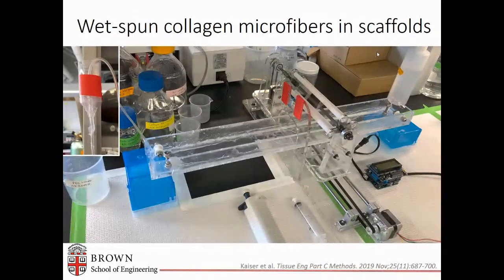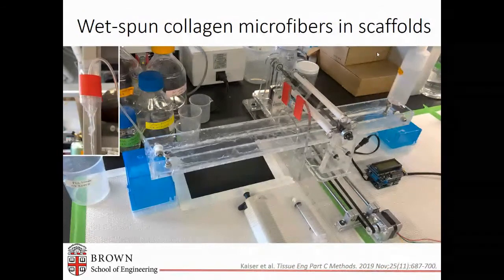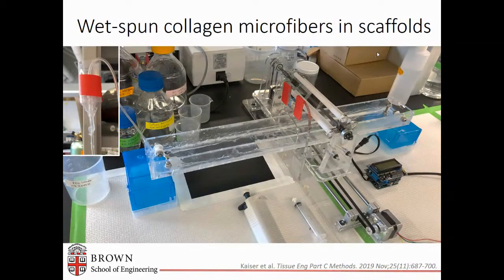In order to provide some geometric cues for elongation and orientation of the cardiomyocytes, we had been using posts, and now we're moving to microfibers. So we're using a technique called wet spinning to create collagen microfibers.